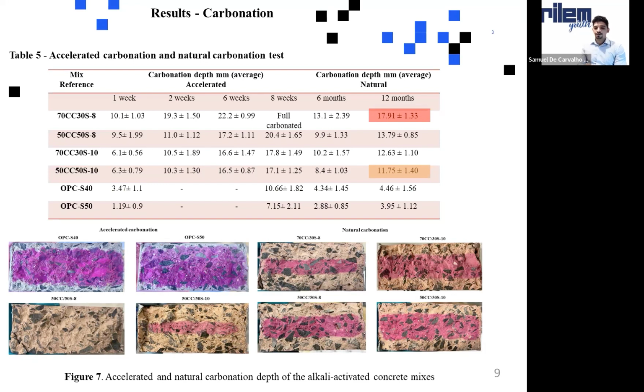So this is for the accelerated carbonation. But when it comes to the natural carbonation, after 12 months, we still have a really high carbonation depth. As you can see, around 17 to 18 millimeters after 1 year. This sample had a really high carbonation depth, which you can also see here. Natural carbonation was very high. However, for the OPC blended with slag, you can see both of the samples after 1 year exposed to the same condition have only around 4 millimeters.